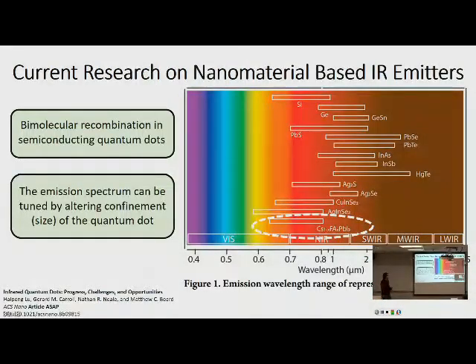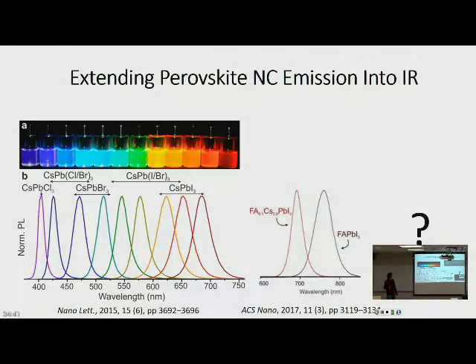And then I just came across this paper. Matt Beard, who was here last semester and gave a talk for MNT, just came out with a review paper on quantum dots that are used for IR or near IR emission. Each white bar corresponds to a certain material, and the range of it corresponds to the tunability of the wavelengths, because with quantum dots, just by changing the size, you can change the band gap. Like I was talking about before, with mercury telluride you can tune between the mid-IR and near IR, and it has the widest breadth of tunability. And near the bottom, we can see that perovskites are starting to make it onto this list now too. I circled that one because that's the material we're going to be focusing on for our simulations.